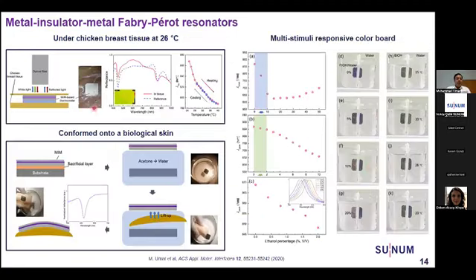And then, as I said, this polymer changes its resonance depending on the temperature. When we put it under chicken tissue at a temperature of 26 degrees centigrade, we see the resonance is exactly the same as the resonance in water at 26 degrees centigrade. We also checked some other temperatures of the chicken tissue, and it behaves the same as in water. So this could be buried in biological tissues to sense the temperature and work as a thermometer.